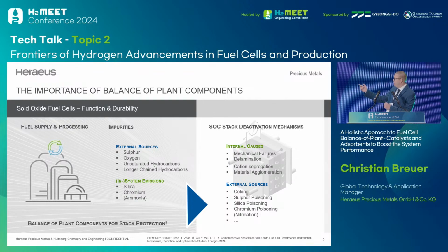And this is especially coking, sulfur poisoning, silica poisoning, chromium poisoning, and depending on what fuel you use, possibly also nitridation. And those are exactly the topics we tackle with the balance of plant components and try to get the stack into a robust, smooth operation.